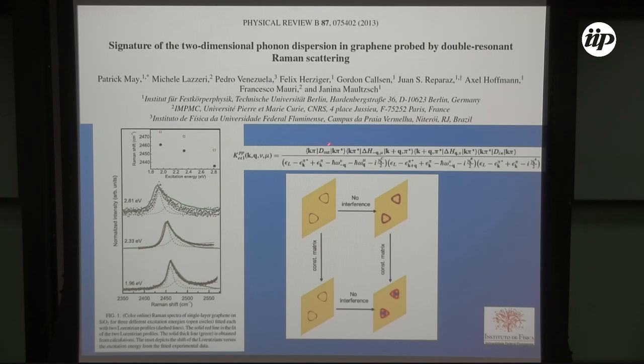Also, I can do the calculation without considering the matrix element. So it's what we call a constant matrix element calculation. So this is the actual calculation, the good calculation. If I turn off interference, I have this. If I take constant matrix elements, I take this. If I do both, turn off interference and take a constant matrix, I have this. And this is exactly here, the K point. So this is the point that the people at MIT claim to be responsible for this peak.